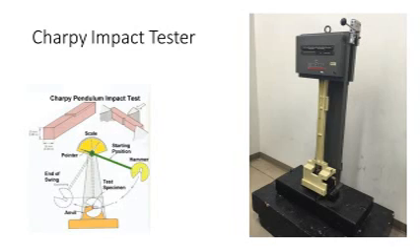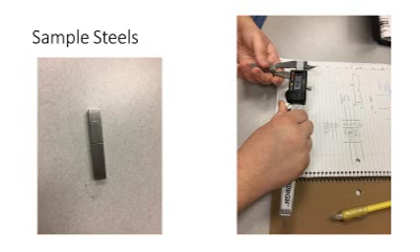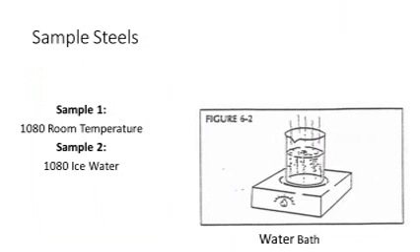In order to find the ductile to brittle transition temperatures, we used the Charpy impact tester. The samples being used are 1080 steels, which have 0.80% carbon taken interstitially among iron. The ones we were using were annealed 1080 steels. The samples were prepared in water baths operating at various temperatures — the water baths were warmed on hot plates for high temperatures and cooled with ice for lower temperatures.